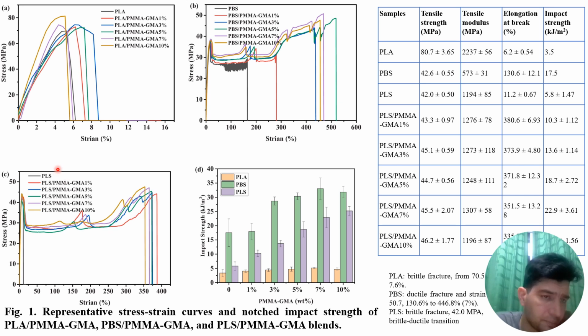After that, the main thing is this one. They made a blend of PLA with PBS, and the different weight percentages of compatibilizer were 0, 1, 3, 5, 7, and 10. So the data show here. The tensile strength of PLS is 42. It is improved to 46. The tensile modulus is 1194 plus minus 85. It also improved. Elongation at break is 11.2. It improved very high.